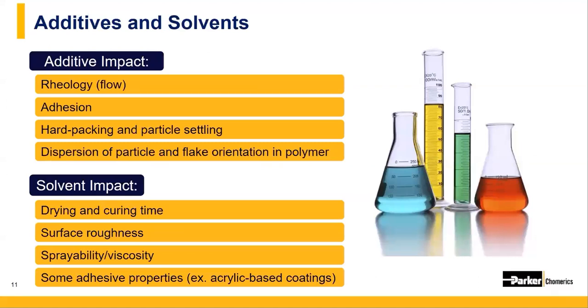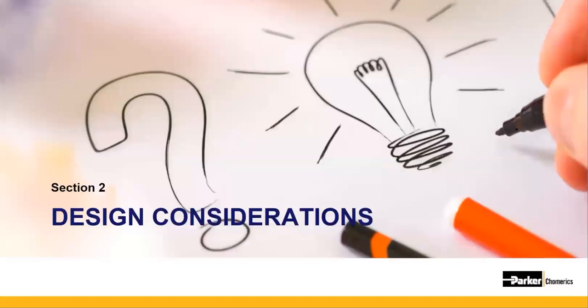Finally, in some instances, such as acrylic binder systems on plastic substrates, the adhesion properties are based on the solvent actually attacking the microscopic surface layers. A stronger solvent, such as MEK, can be mixed into a paint solution to attack the plastic and allow for greater adhesion. Now we'll dig down deeper into factors to consider for your design.